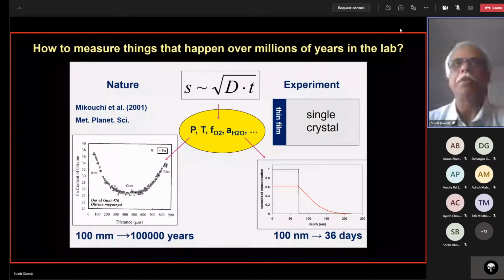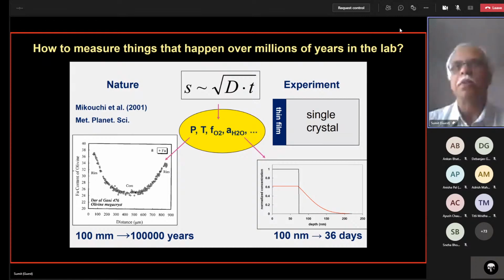So the challenge that we have now is we want to study something in the laboratory that happens over millions of years in nature. Now it turns out that diffusion has this relationship that the diffusion length, S, is proportional to the square root of Dt. What that tells you immediately is that if you have a certain diffusion coefficient, and these diffusion coefficients are properties of minerals, so they depend on pressure, temperature, things like oxidation state or how much water is around, a number of different things. But for a given set of such environmental variables, you have a diffusion coefficient, then the distance is proportional to the square root of time.